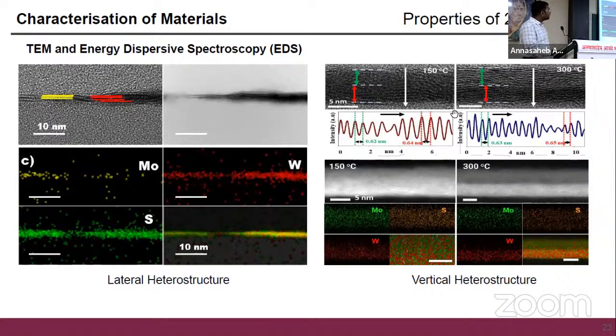The second image is about vertical heterostructure formation. Here you can also see a brightness difference, like bottom and top, which is due to the size of the Mo and W atoms. Depending on size, the brightness in TEM can change. If there is a higher atomic number, it will be brighter because electron scattering will be higher.